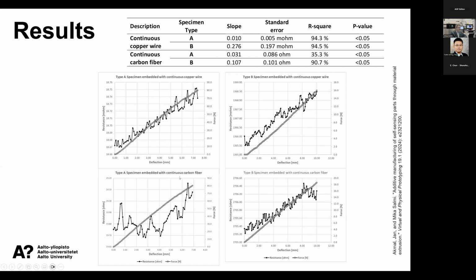This is specimen A with the carbon fiber. Only one wire of carbon fiber, and here you can see that it's hard to say anything because there is so much noise. Only one wire, and you cannot predict too much. But if you have only one copper wire, this follows quite nicely how much you have deflected and what the resistance change is. And then of course, if you want it better, adding more helps, because there are these corners, but you don't get too much better values, slightly better, but not too much.